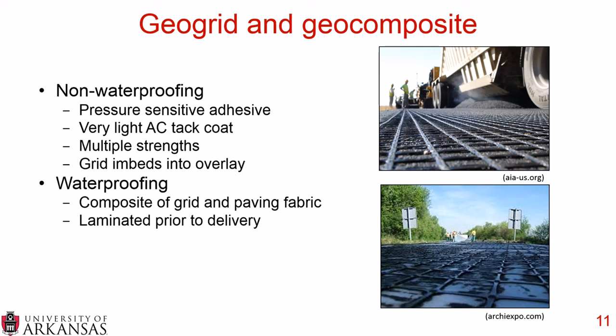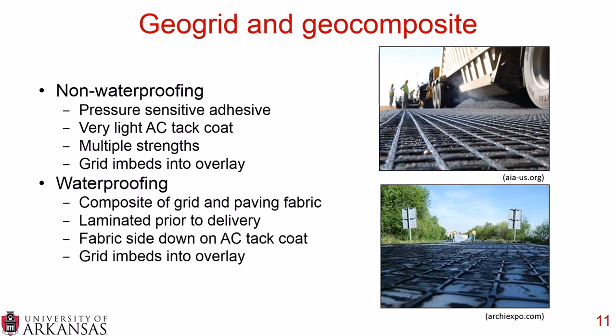For waterproofing options, you can have a composite of a grid and a paving fabric, and it's generally laminated prior to delivery. And you want to make sure to place the fabric side down on the asphalt cement tack coat, and then the grid again embeds itself into an overlay. So you can imagine this open geogrid and geocomposite really isn't waterproof because it has these large cells in it. So if you do want the waterproofing benefits, you want to make sure to use a paving fabric in addition to the geogrid.